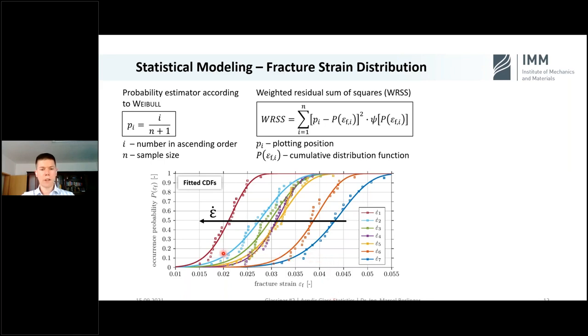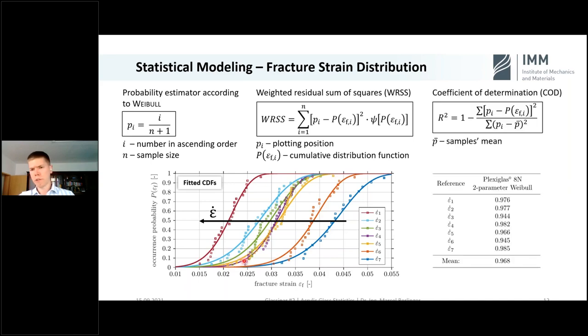And now we do see our effect again: with increasing strain rate, our level of fracture strain drops, and the curves are steeper. That is a measure for the dispersion of the data. The tunnel is getting closer for the fracture occurrence. As a measure for the goodness of our fits, we take the coefficient of determination, which is a good measure to handle, because when the value becomes 1, that's a perfect match, and when the value gets 0, then there is no correlation between experiments and sample. And so we see here in our table that we have a good correlation between measuring points and the CDFs.